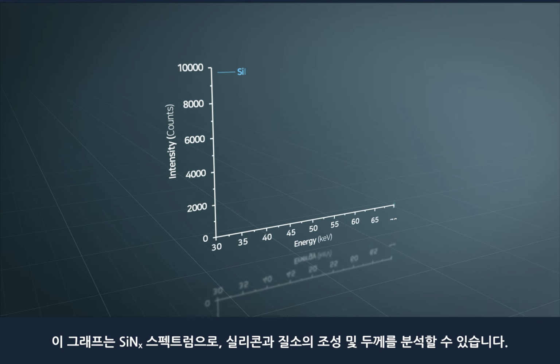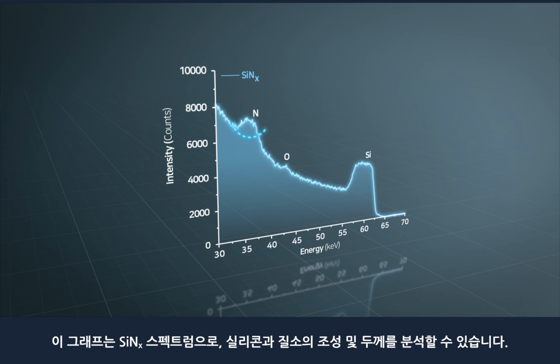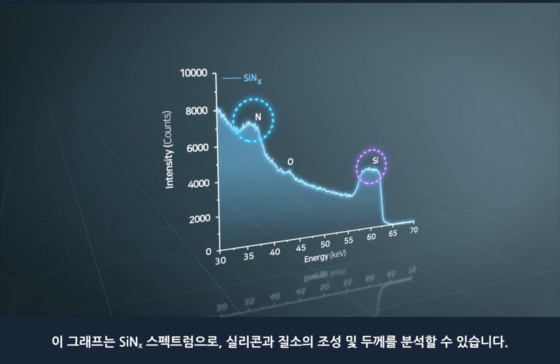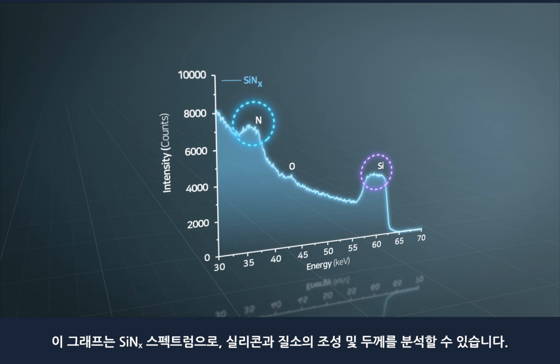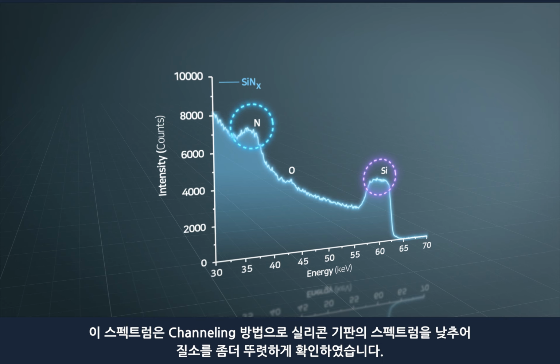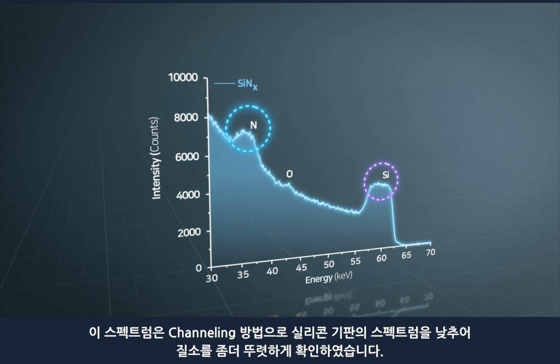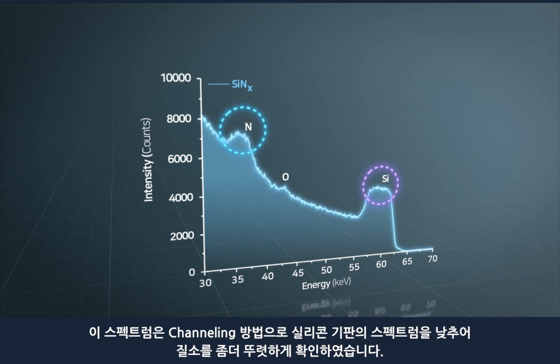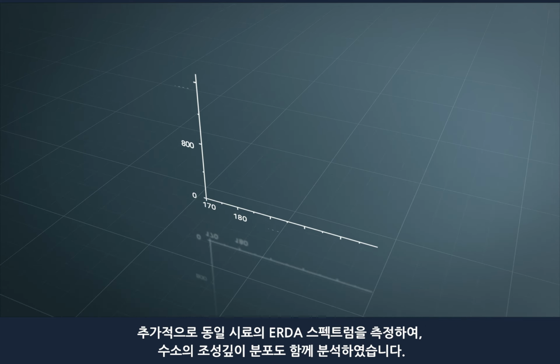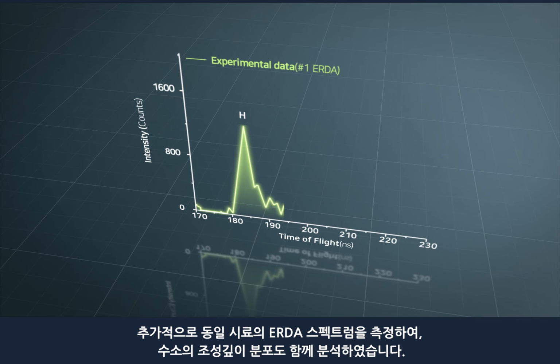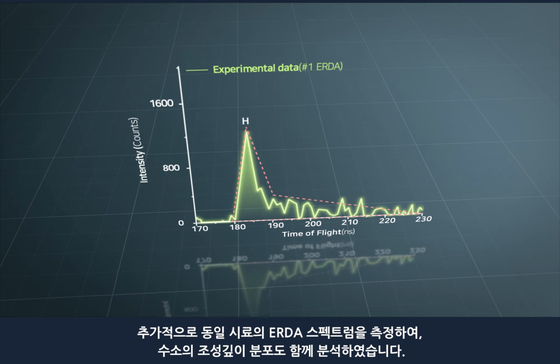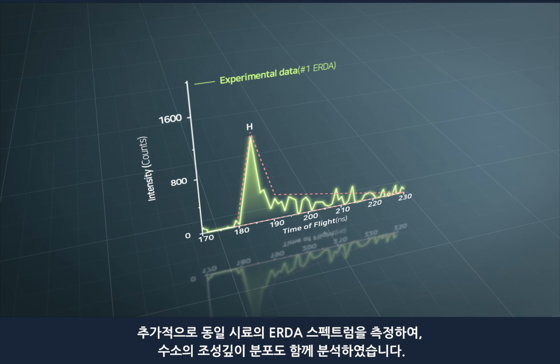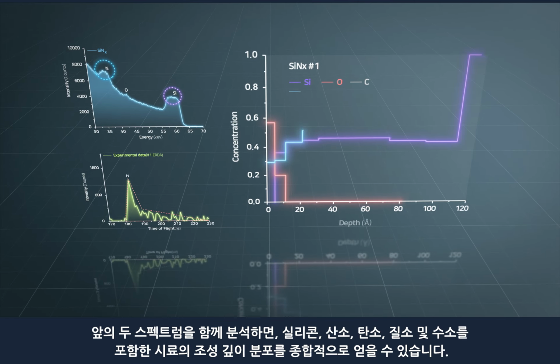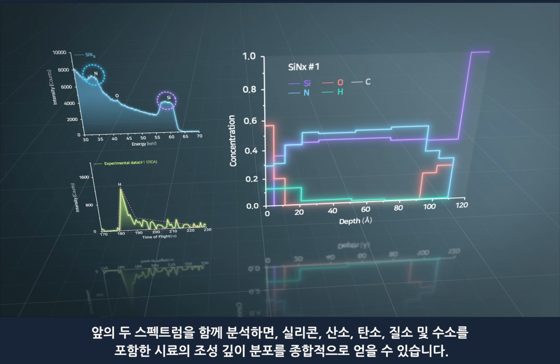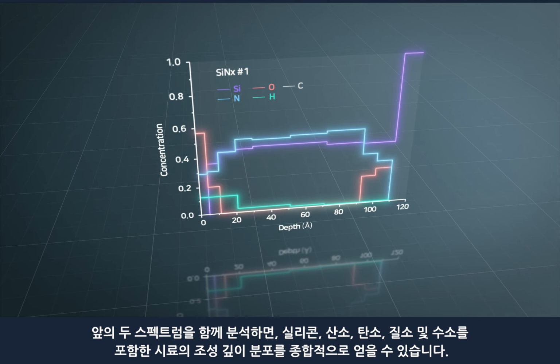This graph shows the spectrum of silicon nitride. Using this spectrum, the composition and thickness of silicon and nitrogen can be analyzed. This spectrum lowered the spectrum of the silicon substrate using a channeling method to more clearly confirm the nitrogen spectrum. In addition, the ERDA spectrum of this silicon nitride sample was measured to analyze the hydrogen profile as well. By simultaneously analyzing the two preceding spectra, the depth distribution of the overall composition, including silicon, oxygen, carbon, nitrogen, and hydrogen could be obtained.